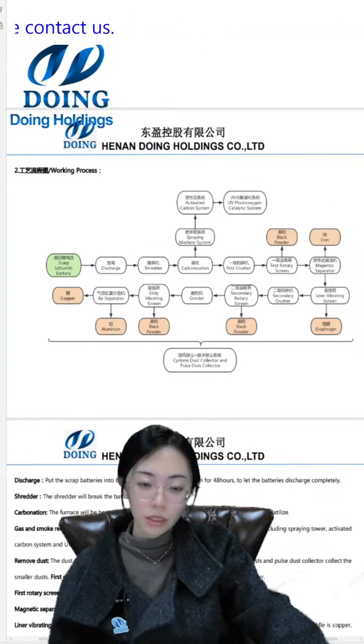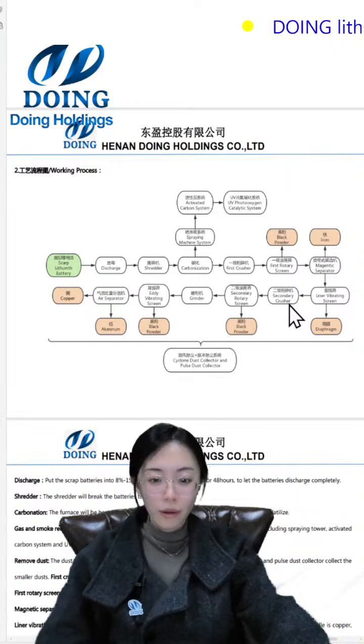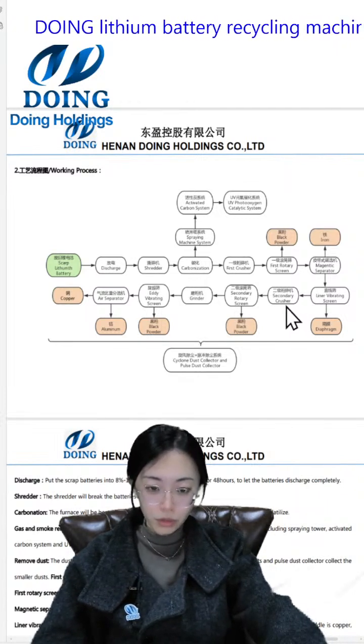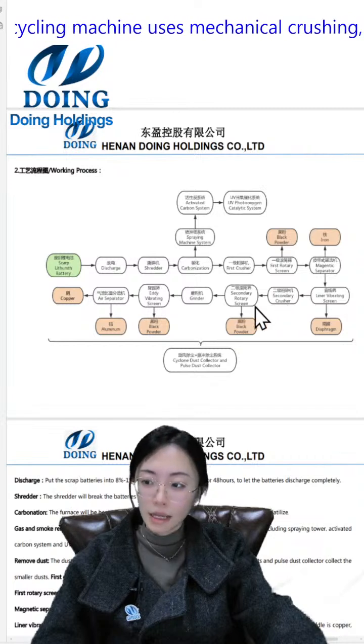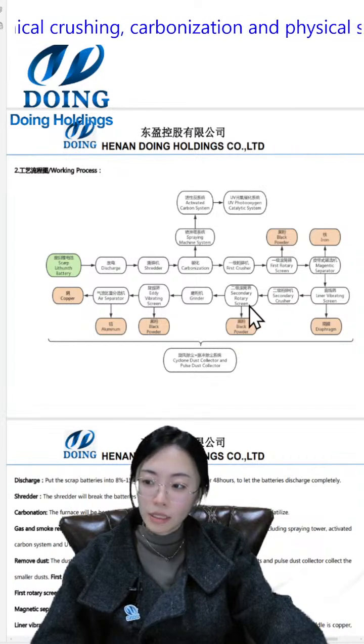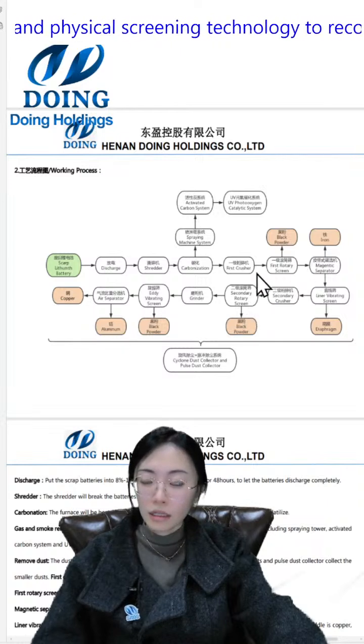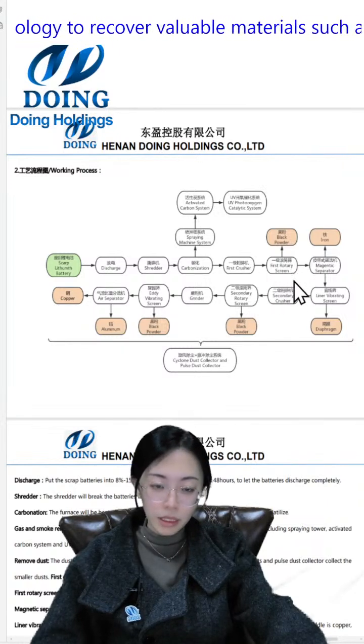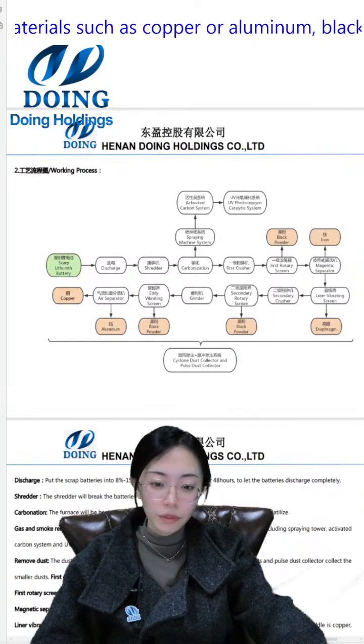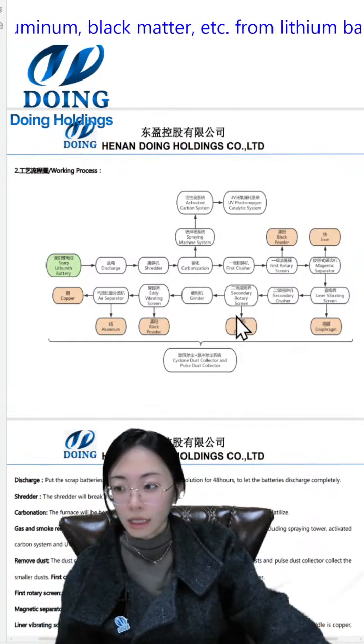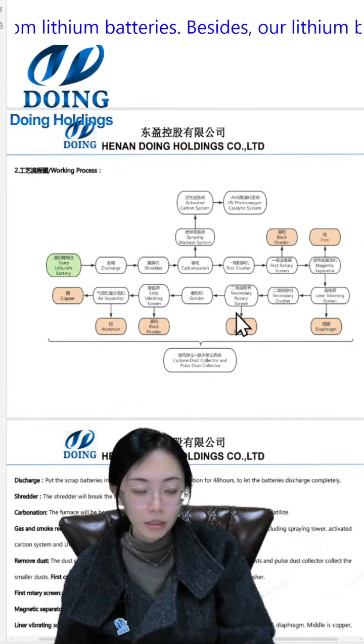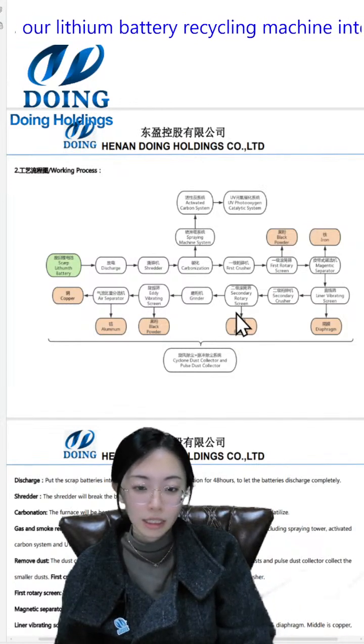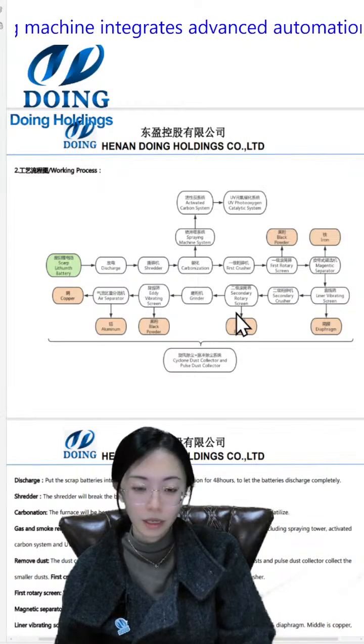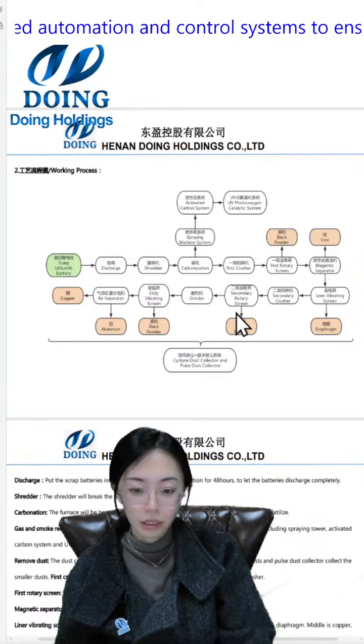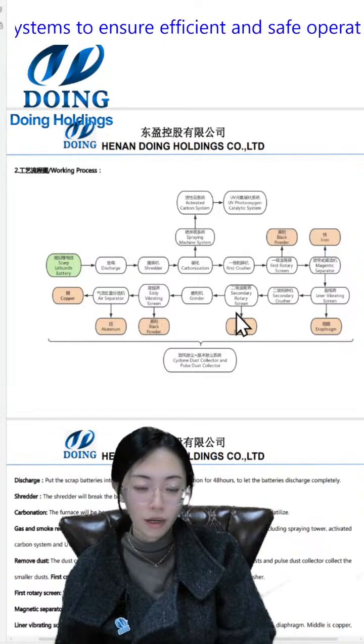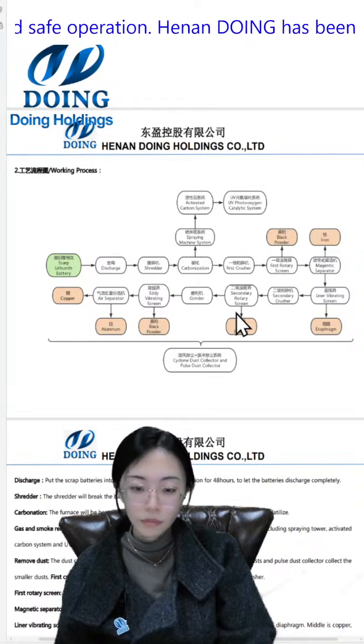And then we will go into the second hammer crusher to crush the materials to 6 millimeter, and then the second rotary screen, which is a little smaller in size than the first rotary screen. This is 6 millimeter and this is nearly 4 millimeter. In this step, the recovery rate of the black powder is nearly 95%. The mesh in this step is 140 mesh. Then comes the grinder.